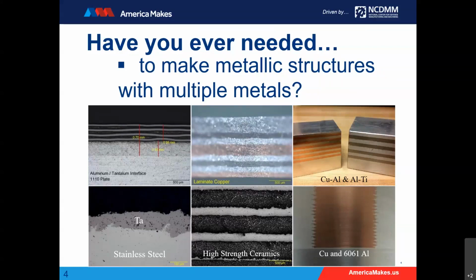Typically they're all metallic. The picture on the right shows layers of aluminum and titanium, aluminum and copper, but we can get into more exotic materials like tantalum, tungsten, moly, Invar. All those different metals can be combined into a single print job. Now, you might be asking, why would you want to do that? Typically, we're trying to use the strengths and weaknesses of each material where they're needed. So for the aluminum and copper, we often use copper right where there's a heat source and a heat exchanger.